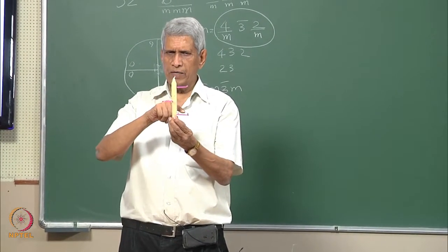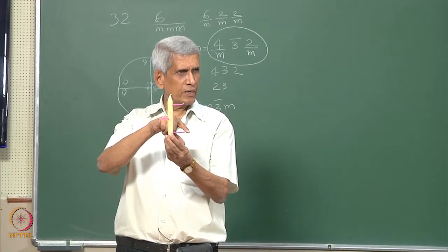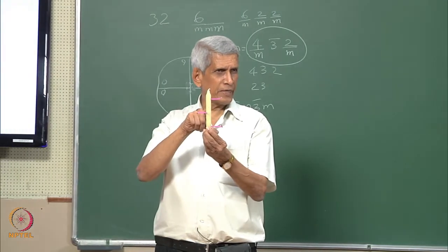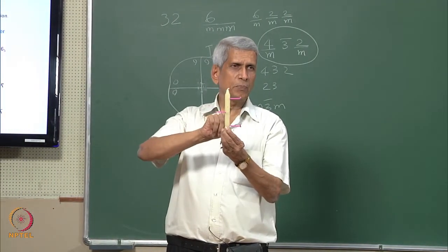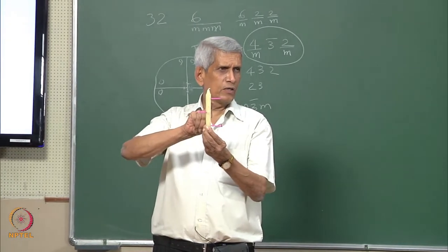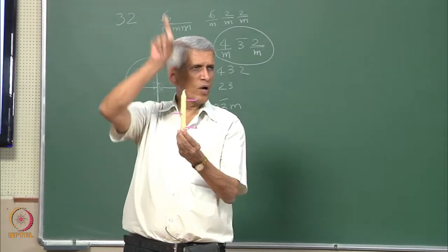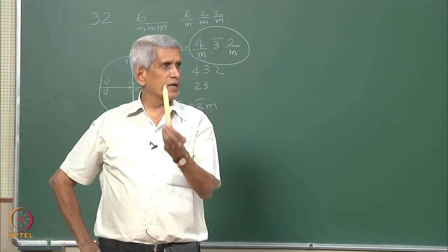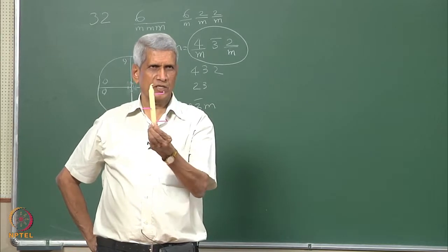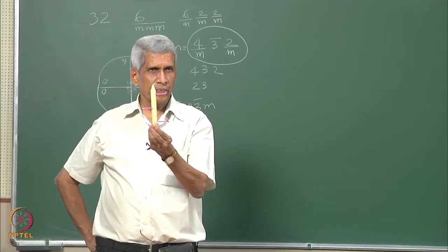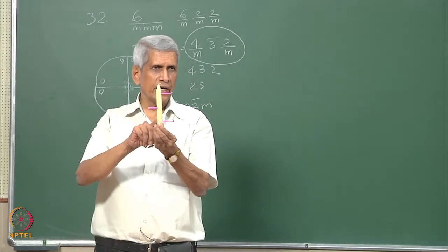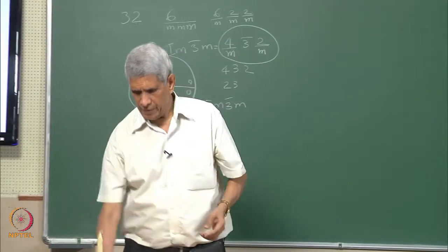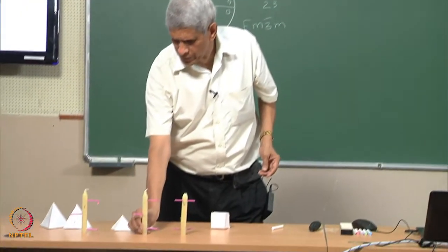In between we have a point which has been rotated by 180 degrees but shifted by half the lattice parameter. Again in this particular direction you notice that this has a screw axis associated with it in the lattice. These sort of symmetries are exhibited by many molecular crystals. There is a convention which is followed to represent it, that we will come to.